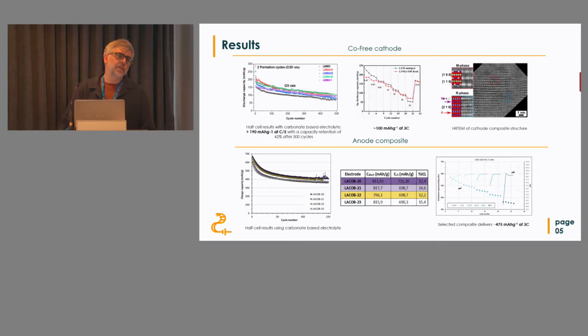We are realizing that depending on the dopings that we are using, we are changing from a segregation of the different phases, the rhombohedral and the monoclinic, to the formation of nanodomains within the particles, which is affecting the performance of the electrode materials a lot.